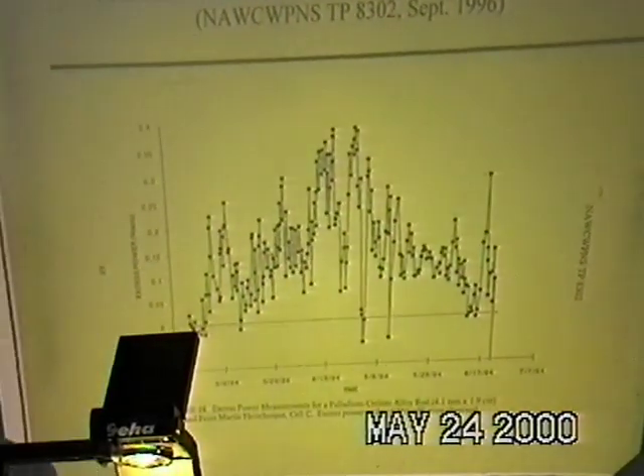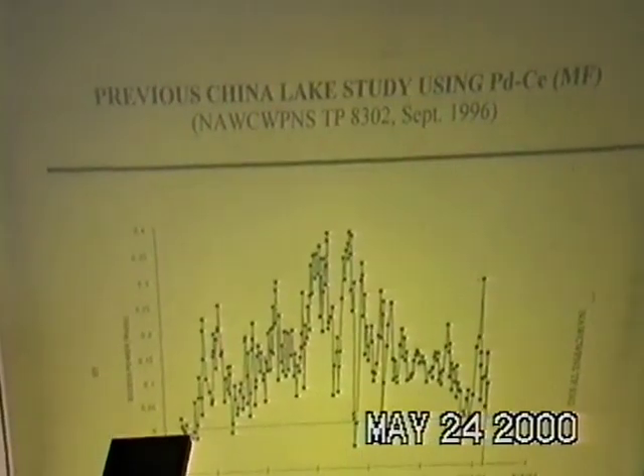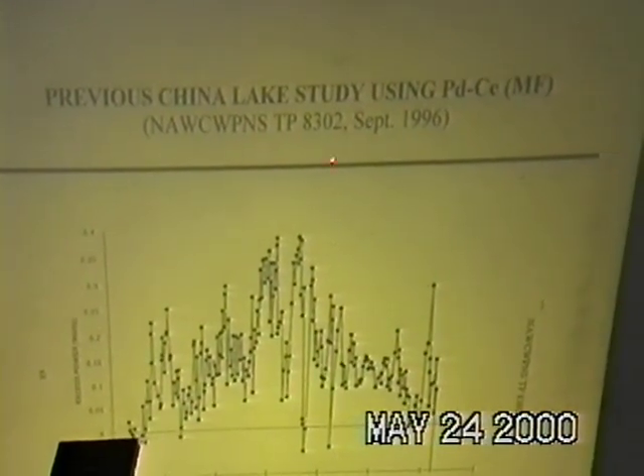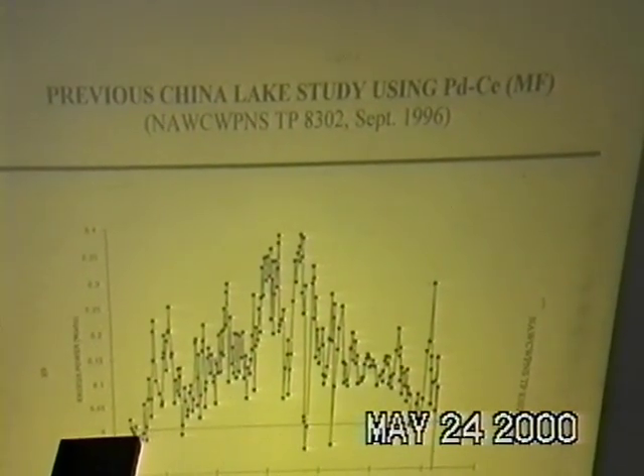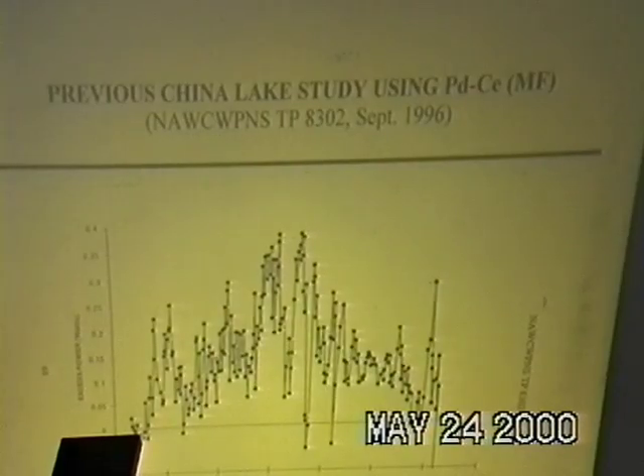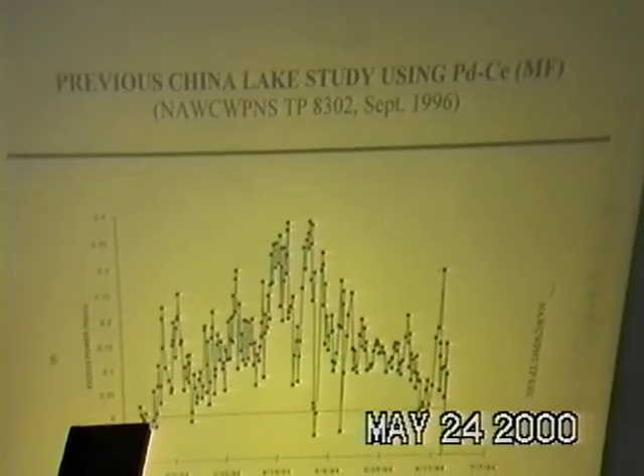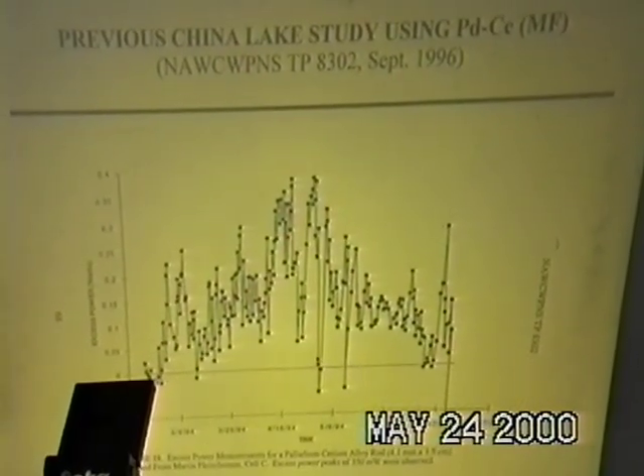The palladium cerium also produced excess heat in China Lake. This is from the Navy report in 1994, 1995. Well, this is 1994, the data shown here, but it showed considerable excess heat, the palladium cerium rod. I used exactly the same rod again in Japan and also got excess heat. The palladium boron was a different palladium boron rod that I used in Japan than what I showed previously, however.